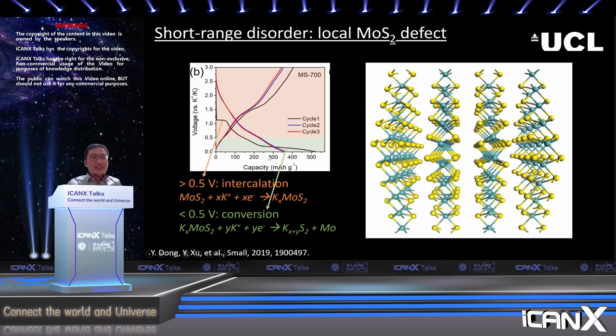At the discharge voltage that is higher than 0.5 volts, the material undergoes an intercalation process where the ions are intercalated into the interlayer space between the molybdenum sulfide layers. At the discharge potential that is lower than 0.5 volts, which is the green area over here, the molybdenum sulfide is reduced to molybdenum metal and potassium sulfide. This part contributes a very significant part of the capacity of the material.